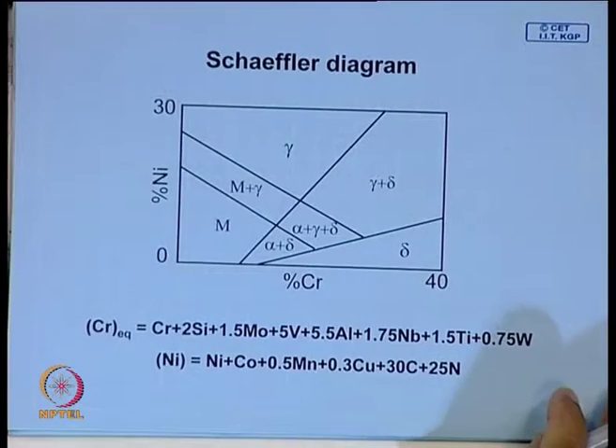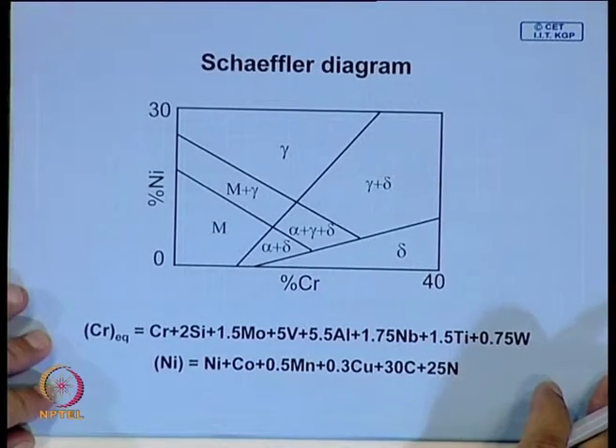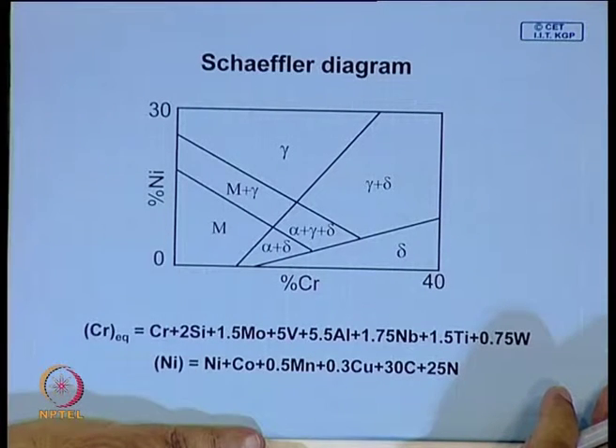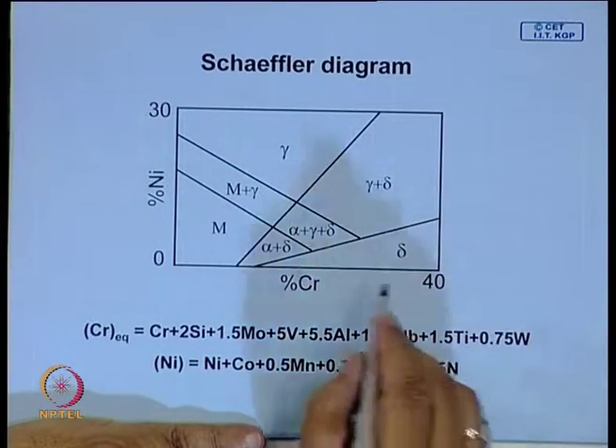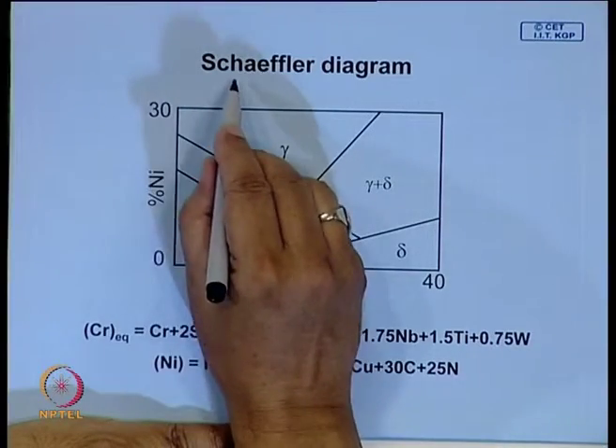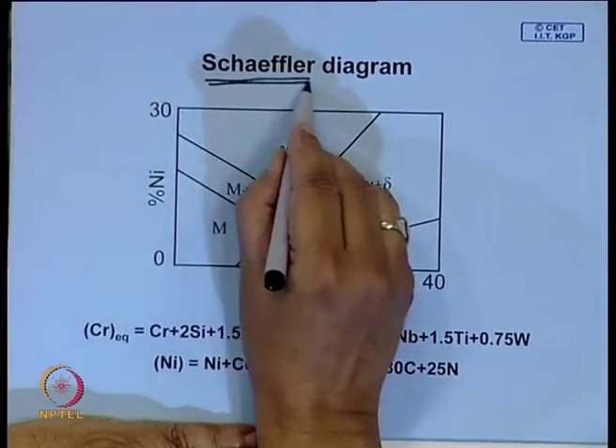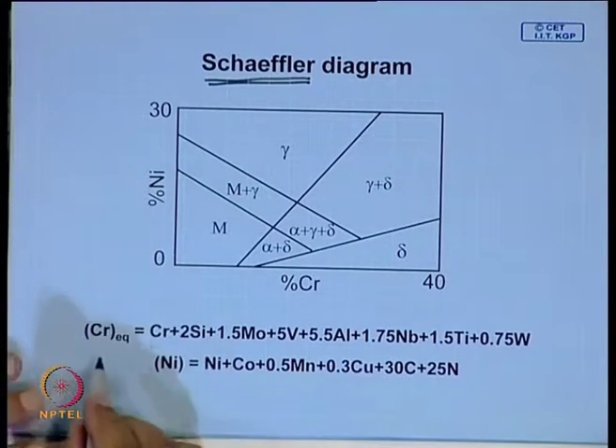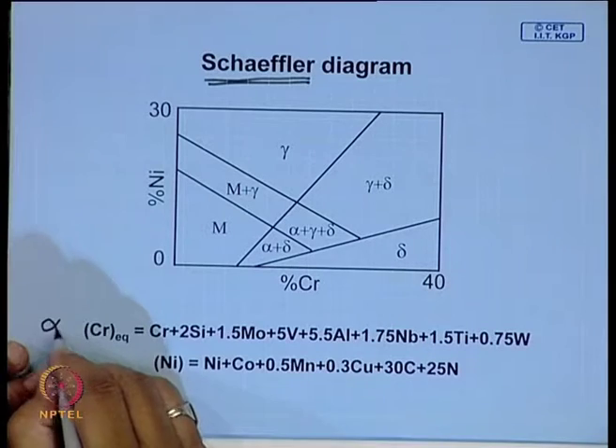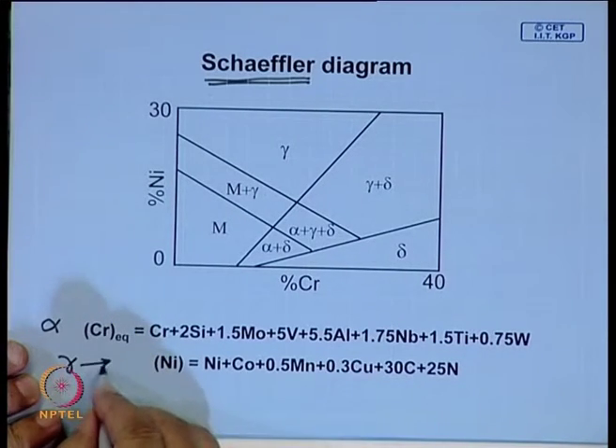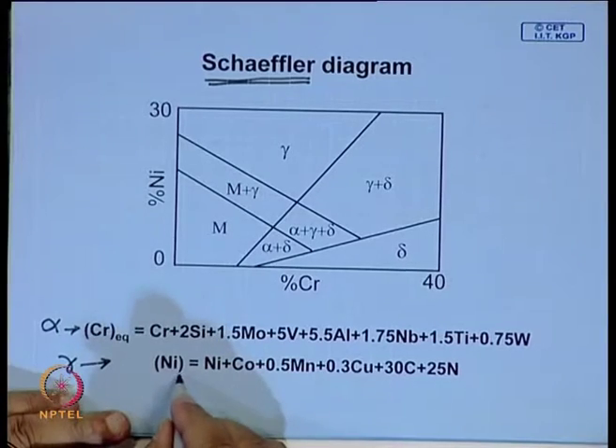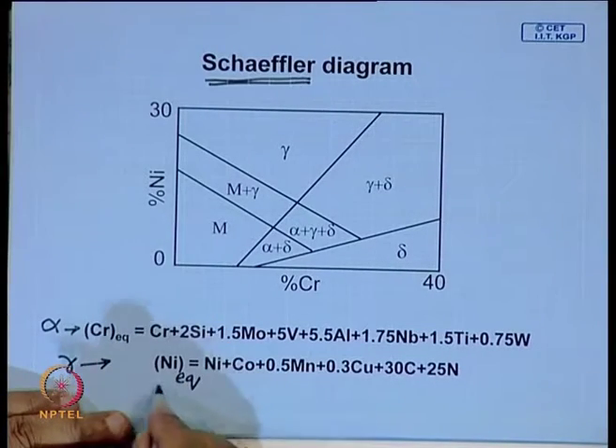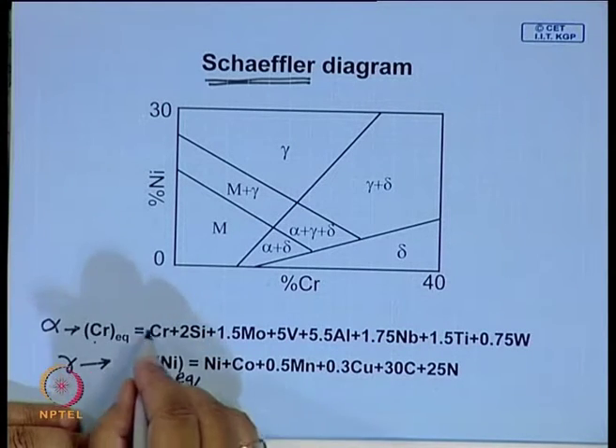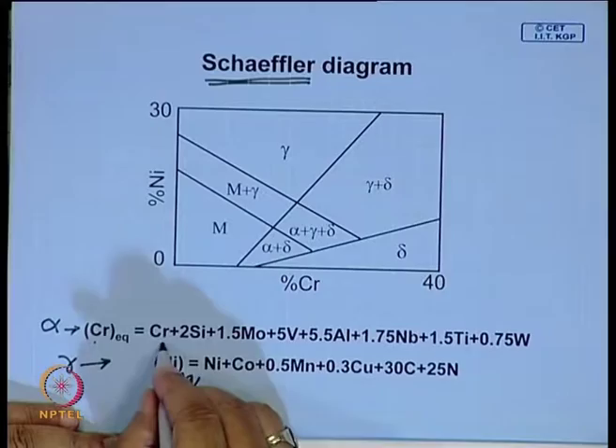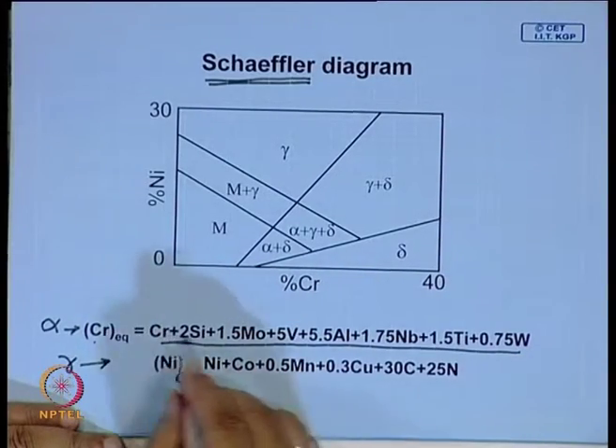Now, to look at what will be the structure of the steel, whether it will be ferritic, whether it will be martensitic, or in the extreme case will it be austenitic, that is represented very well by a diagram called the Schaeffler diagram. So, all alloy elements can be grouped into two parts. One is which stabilizes ferrite, another which stabilizes austenite. And what you can find out is nickel equivalent or chromium equivalent. So, they stand for all ferrite stabilizers, with the factors given here.